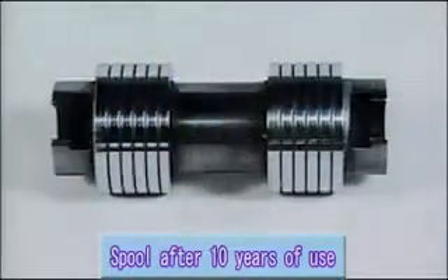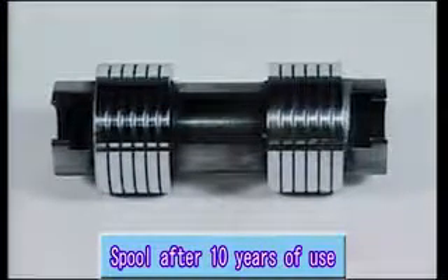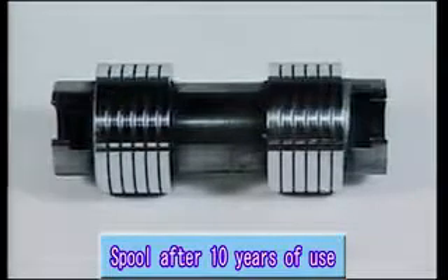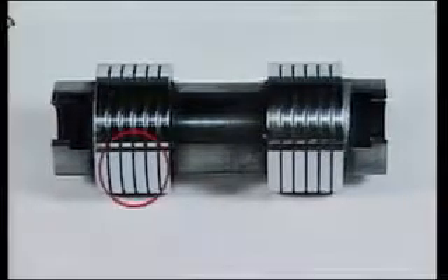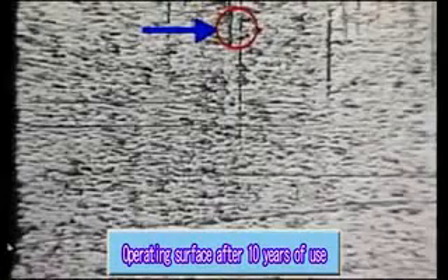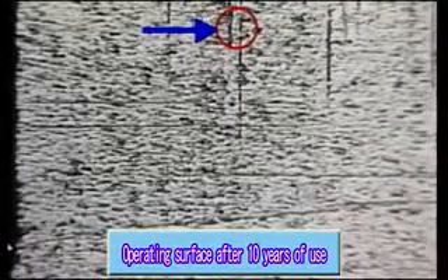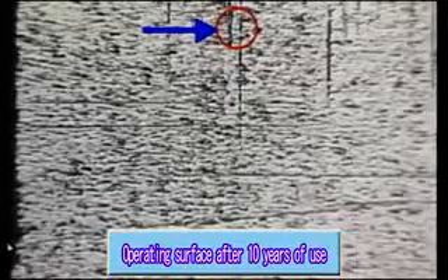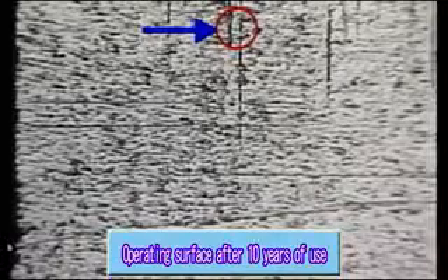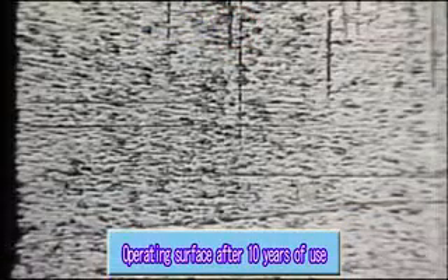We investigated the operating surface of the spool that has worked without failing using this oil 10 years after it began operation. As you can see in this microphotograph, there are no horizontal scars in the operating direction, and the vertical processing scars of when the part was new, shown by the arrow, still remain. When this is compared with a new part, it is easy to see that there is extremely little friction and it has a smooth operating surface.